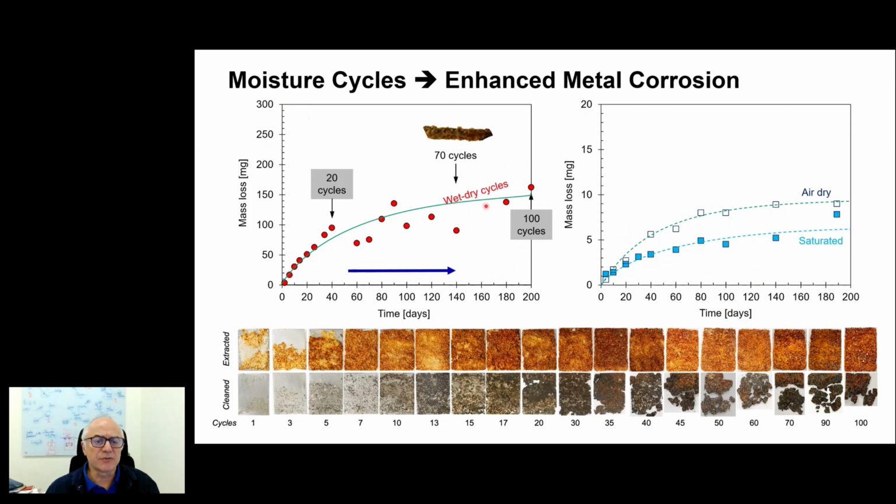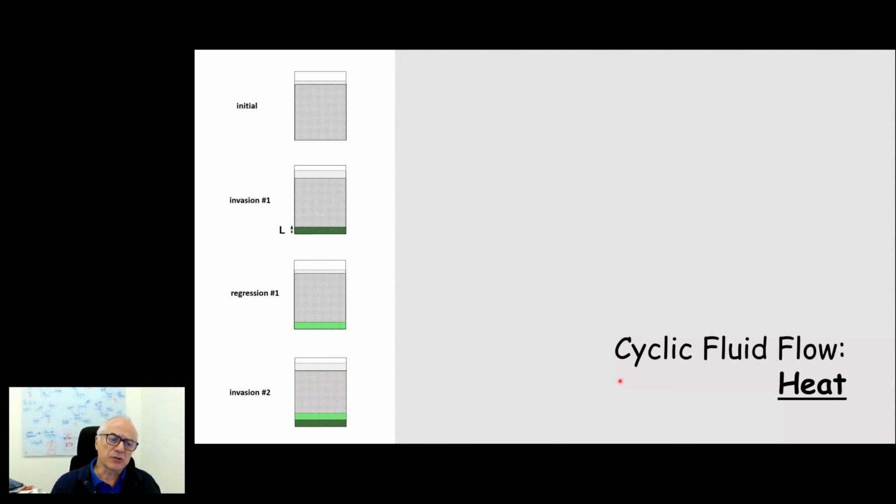When there is cyclic fluid flow, we bring the oxygen that will support the corrosion, and we remove the corrosion byproducts, dramatically accelerating corrosion. Therefore, where the water table is oscillating is where we should anticipate the maximum corrosion, and indeed that is well known and proven here with this data, beautiful data by Dr. Gloria Castro.